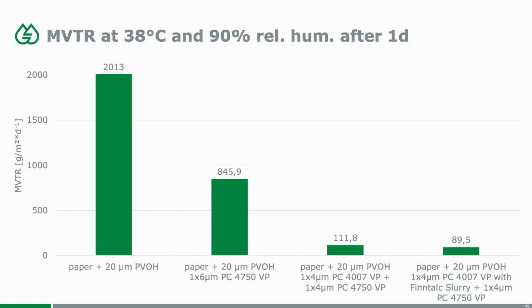But then if you go and check the MVTR properties under tropical conditions, you see that the paper with the PVOH on its own has no MVTR barrier. So you have 2000 grams per square meter per day. That does not provide any protection whatsoever. If you then just coat these PVOH coated paper with 6 microns of PC4750, you are able to bring it down to 850, which is again not bad, but comparing the results that we've seen in the slides before, a little bit disappointing. Then if you choose to coat it with a two-layer system, first starting with PC4007 as primer, followed by the top coat with 4750, you bring it down to 110.